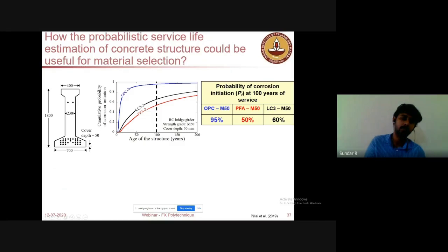And if you look at 50 years as a service life, we could see that the probability of corrosion initiation is under 50%. So these are a better choice of binders for a concrete element, for example a girder element to be constructed in a place where chloride induced corrosion is more prone, like in marine structures. So it is always recommended to go with PPC, Portland Pozzolana cement, or other ternary blended systems.